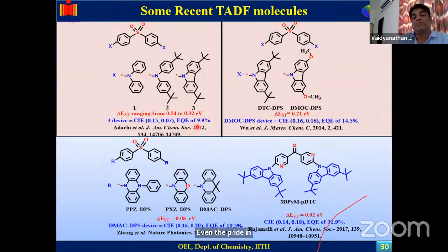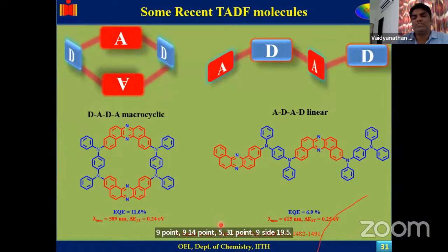You can see the external quantum efficiency is more than 5%: 9.9, 14.5, 31.9, 19.5. So it's very promising results that one can see. It's also possible to connect the acceptor-donor in this type of linear and cyclic structure. In the cyclic structure, you get a higher external quantum efficiency, whereas the linear structure has 6.9%. So this is also a very interesting thing that one needs to consider.